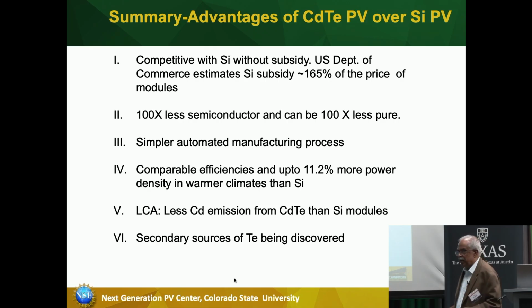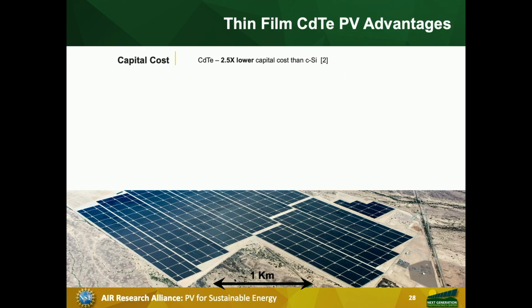And there is also a concern about the availability of tellurium. Tellurium is not a rare earth, not the rare sense. It is one of the rarest elements on Earth. It's on the same level as platinum. So there is one project we have where we are trying to reduce the amount of tellurium. It's no problem short term, but long term, if we want this technology to be as voluminous as silicon, we need to solve this problem of tellurium being this rare. So thin film advantages: 2.5 times lower capital cost than c-Si.